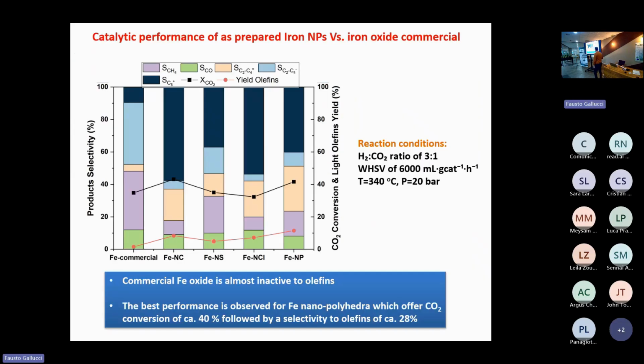And here we can see the CO2 conversion and the yield to olefins over an iron commercial sample, iron nanocubes, nanospheres, nanoclusters, and nanopolyhedra. And we can see that nanopolyhedra exhibit the best performance, offering about 40% of carbon dioxide conversion and a selectivity to olefins of 28%, yielding an olefins yield of about 10% to 11%.